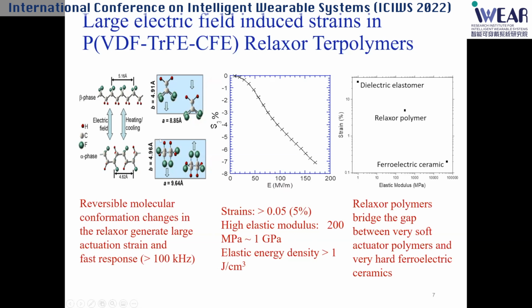Such a large change in strain is really due to reversible conformation change between the polar ferroelectric conformation and the non-polar conformation. You can see there's a large dimension change when you go from the non-polar to polar phase. And also, the response is pretty quick, about 100 kilohertz. So it's very encouraging.